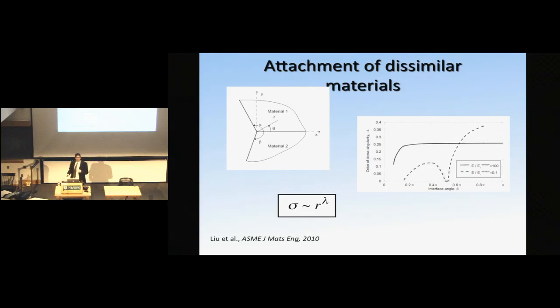Other ways you can do it are rubbing the gum on your pants to get a little bit of a gradient in there. Then with a lower mismatch in stiffness, the singularity damps down. And then if you're lucky to find an old table with lots of teeth sticking out so that the wood can interdigitate into the gum, that works too. So the body actually uses all three of these mechanisms.